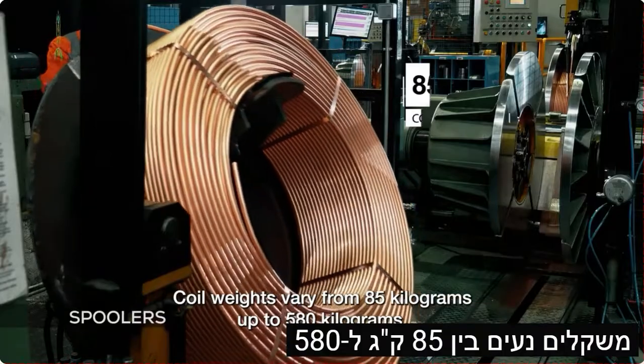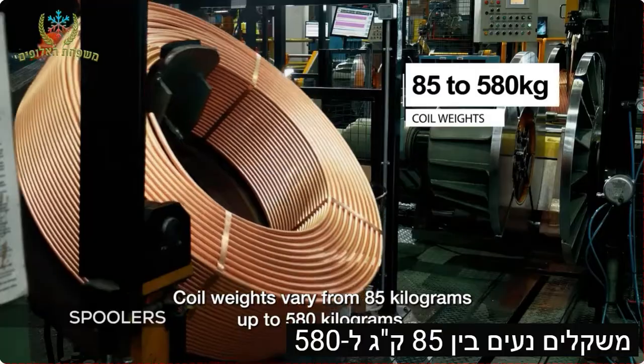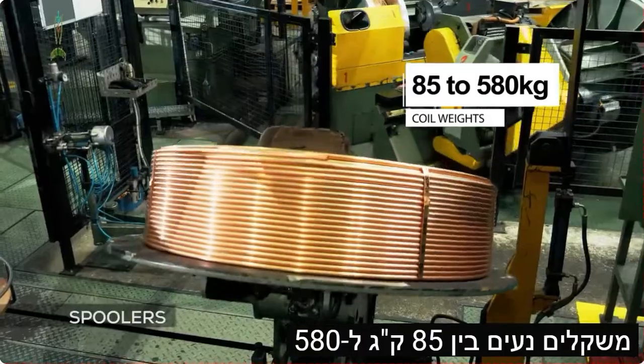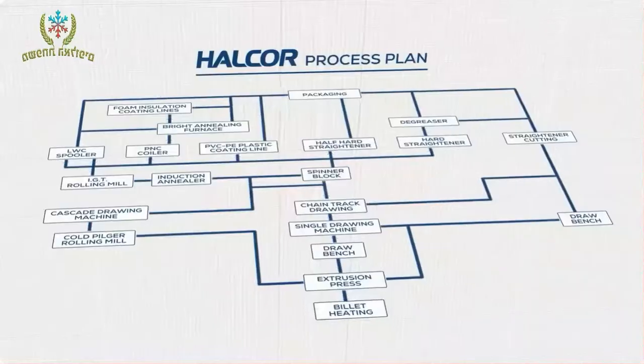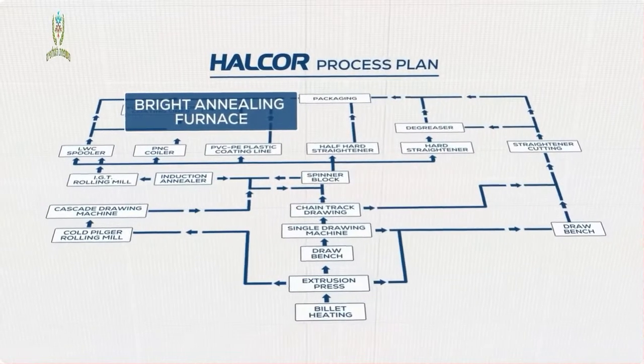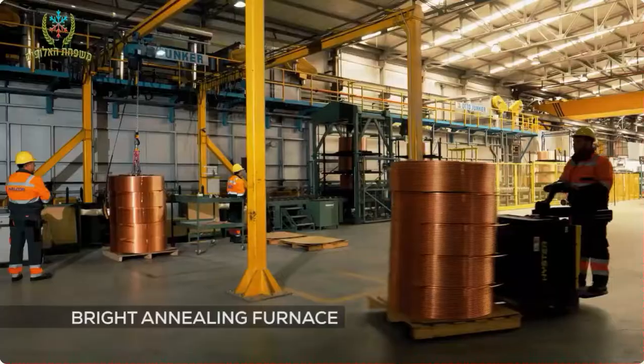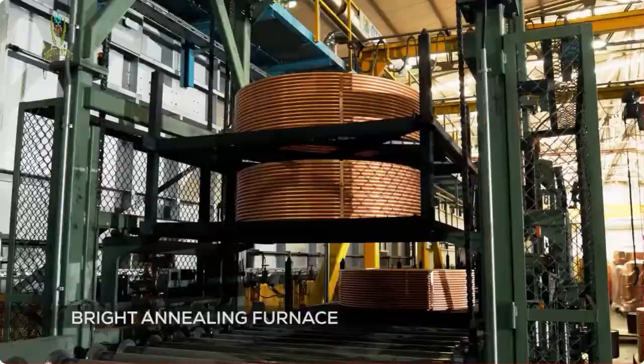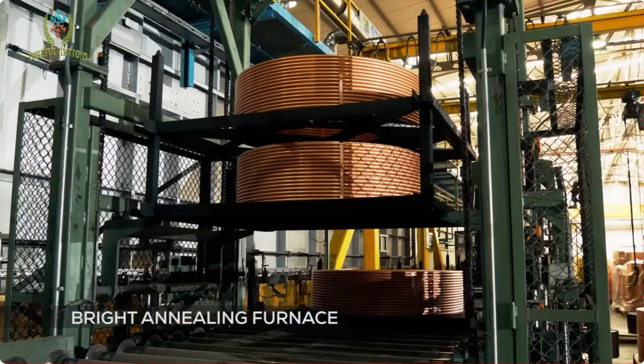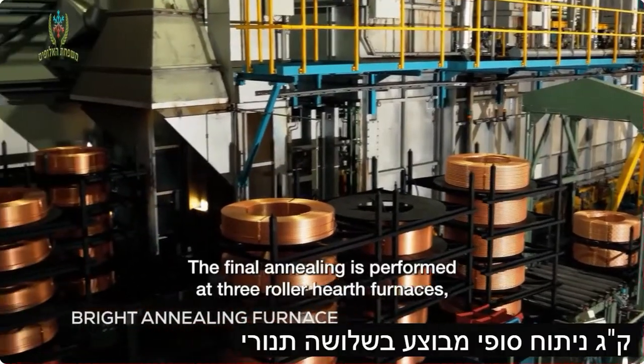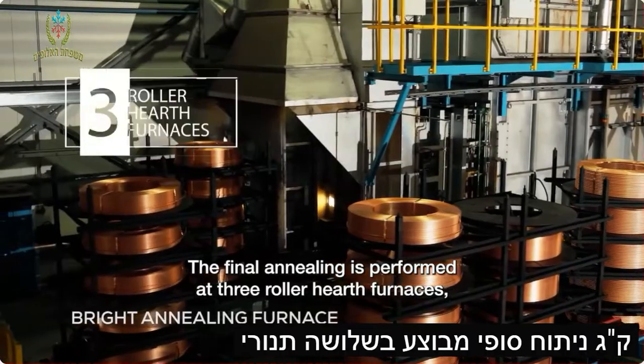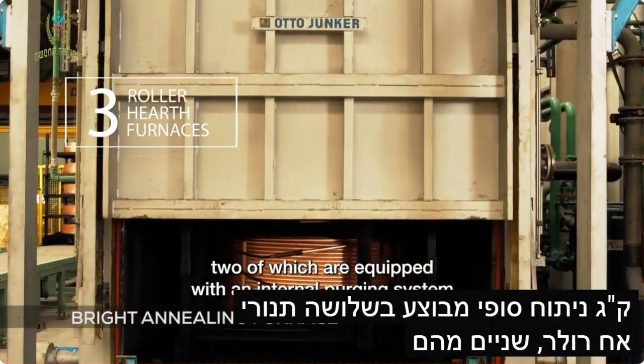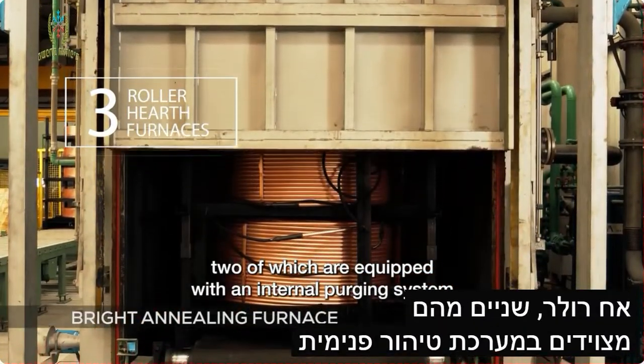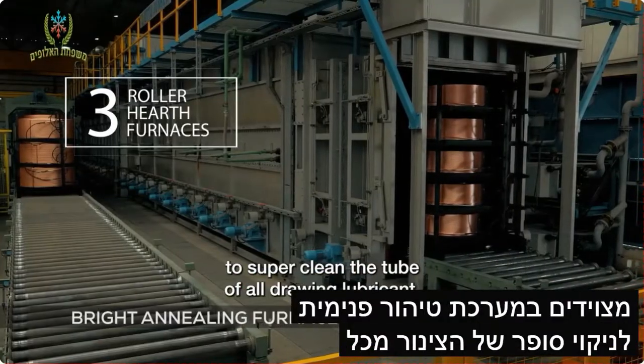Coil weights vary from 85 kilograms up to 580 kilograms. Final annealing is performed in 3 roller hearth furnaces, 2 of which are equipped with an internal purging system, to super clean the tube of all drawing lubricant.